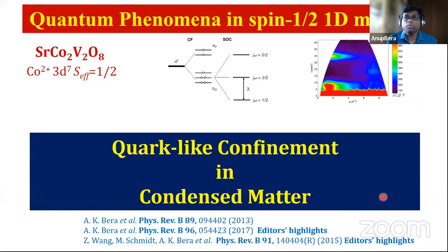Now I'm coming to the compound which is spin half, based on the cobalt 2+ ion. As the discussion was, cobalt is a 3d element and has a small spin orbit coupling. Yes, if we don't consider the spin orbit coupling, due to the crystal field we know that the ground t2g state has a lower energy and eg has a higher energy, so 3 unpaired electrons can be arranged here. But when we introduce the spin orbit coupling, this energy state is rearranged and the lowest energy state becomes J effective equal to spin half.